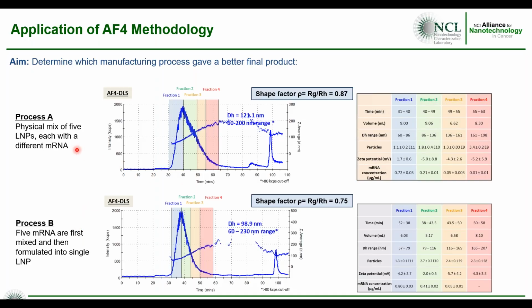So for process A, which is a physical mix, we collected each of the fractions coming off AF4. We looked at particle count, size, zeta potential, and mRNA concentration, as well as calculated the shape factor. We did the same thing for process B, and the results are shown here.